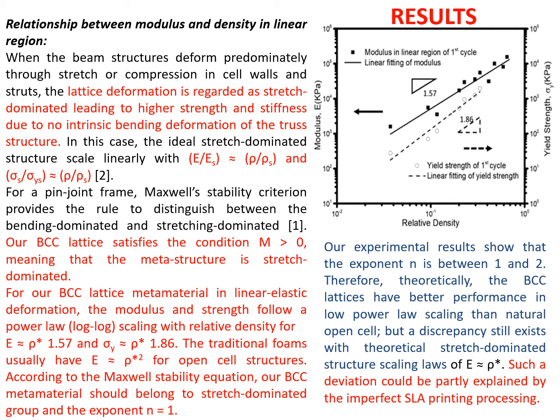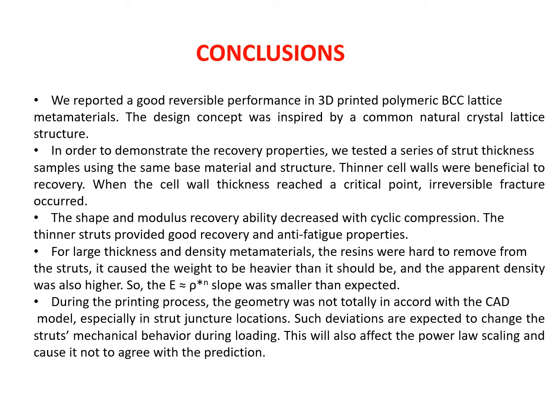Therefore, theoretically, the BCC structure has better performance in low power-law scaling than natural open cell, but the discrepancy still exists with theoretical stretch-dominated structure scaling laws. Such a deviation could be partially explained by the imperfect SLA printing process. So in conclusion, we can say that we have a good reversible performance in 3D printed polymeric BCC lattice metamaterials. The design concept was inspired by a common natural crystal lattice structure.